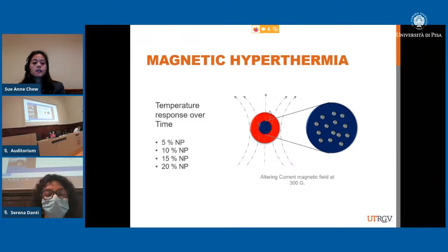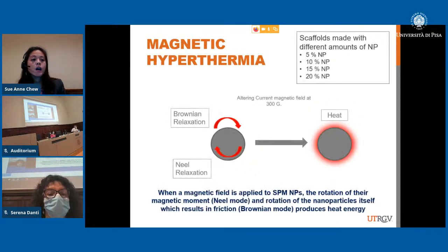So how it works is we have the scaffolds, and we use the globular scaffolds because we found that with that one we were able to more easily take in the nanoparticle, given the shape of it. So that scaffold right now, we're making it with different amounts of nanoparticle. We have 5, 10, 15, and 20%. And when an alternating current, so an AC magnetic field, is provided to the scaffold using a magnetic hyperthermia machine, we see that because of Brownian relaxation as well as Néel relaxation, the particles can provide heat and can heat up the scaffold.